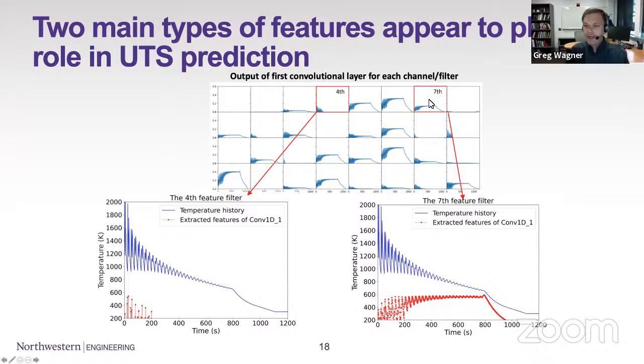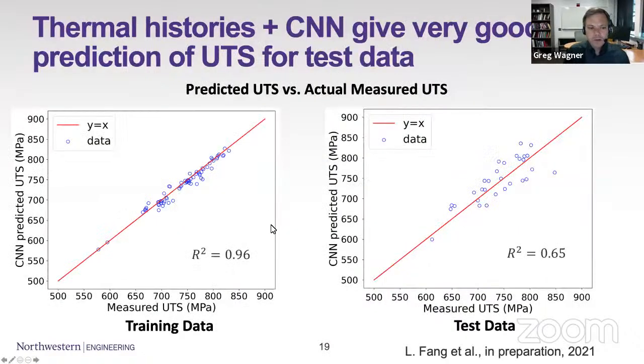But there's also another class of features, the seventh feature, that's being picked out that has something to do with how much time is being spent in that intermediate temperature range. And again, exactly what that is, this CNN can't tell us, but it is telling us that there is a clear correlation between that feature and the UTS. If we train our network using that data, the training data, which we expect to be a good match because we're fitting it. But if we take that model and apply it to the test data that we've set aside, we find that now, unlike that cooling rate prediction, our predicted UTS is actually very good.